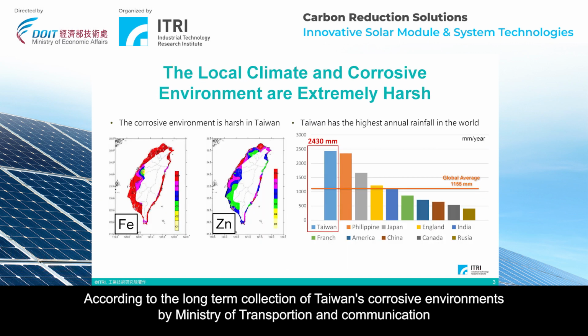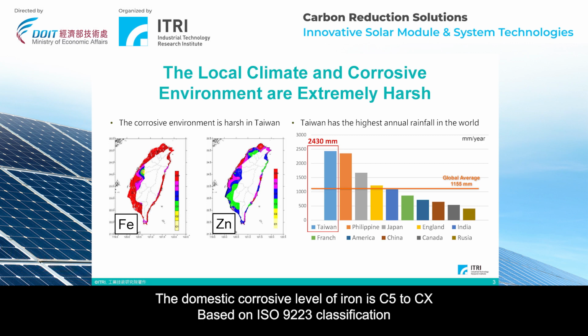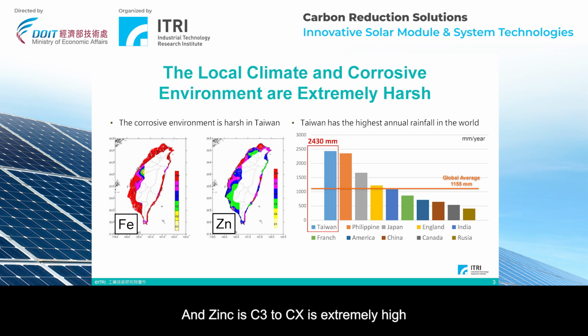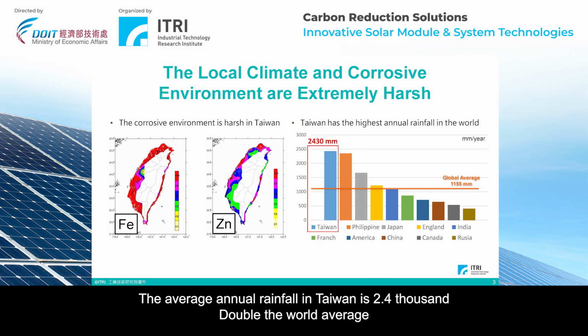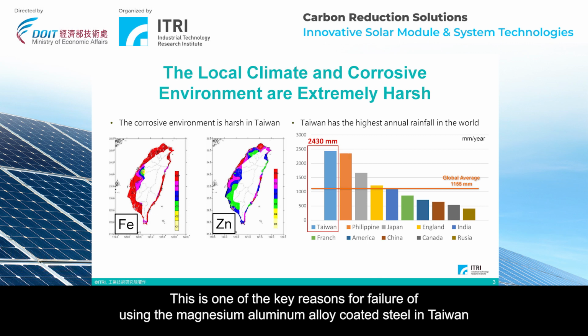According to the long-term collection of Taiwan's corrosive environments by the Ministry of Transportation and Communication, the domestic corrosivity level of iron is C5 to CX based on the ISO 9223 classification, and of zinc is C3 to CX, which is extremely high. One of the reasons is the rainfall. The average annual rainfall of Taiwan is 2.4 thousand millimeters, double the world average. This is one of the key reasons for the failure of magnesium aluminum alloy coated steel in Taiwan.